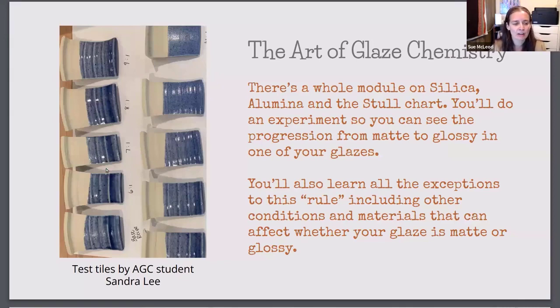And so as she increases silica, it goes from matte into glossy, glossy, glossy, glossy, and then it starts to become under fired. And you can see that this one here is definitely under fired, just kind of in the reflection.